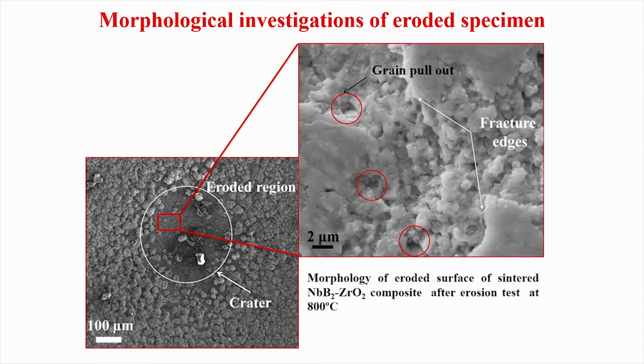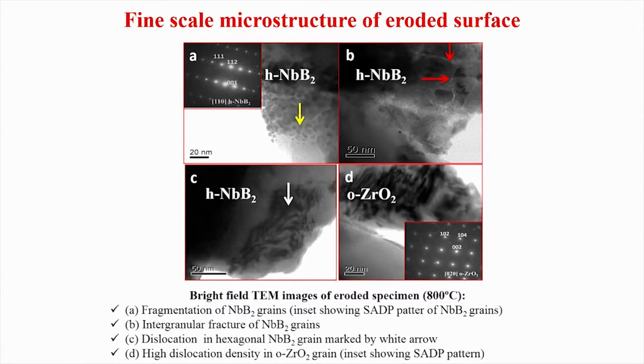At 800 degree Celsius, you remember that from room temperature to 400 to 800, the wear depth decreases, and what it means is that either these alumina particles are covering the entire material surfaces, and even after ultrasonic cleaning they are embedded very strongly. And the second thing is that perhaps at 800 degree Celsius, at higher temperature, the ceramic is not prone to brittle fracture anymore, because at high temperature there may be some deformation possible. And that is why, although grain pull out and fracture edges are observed, the severity of wear is certainly lesser than at room temperature or 400 degree Celsius.